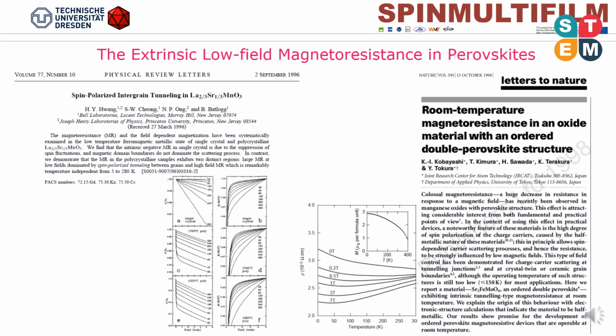The extrinsic low-field magnetoresistance in perovskites was discovered by Hwang et al. in 1996 in polycrystalline lanthanum strontium manganite ceramics. It was shown that the magnetoresistance in polycrystalline lanthanum strontium manganite ceramics exhibits two distinct regions: large magnetoresistance at low fields dominated by the spin polarized tunneling between the grains, and the high field magnetoresistance obtained also in single crystals.